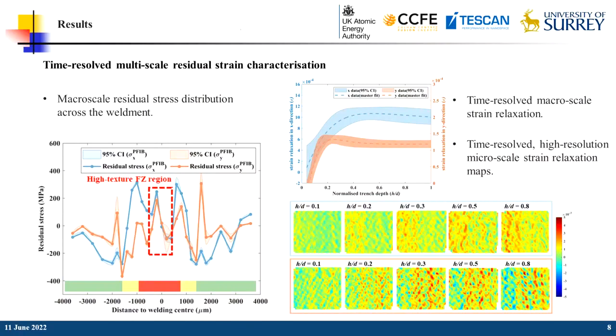And the macroscopic residual stress distribution is then characterized by the PFIB-DIC ring-core method in two directions, in the X direction as well as in the Y direction. So the time-resolved macroscopic strain relief curves and the maps of the strain relaxation are shown as example on the right-hand side of the page.